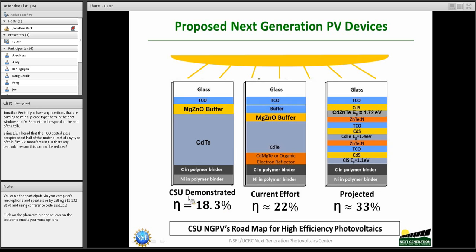And what we have demonstrated and verified by the Newport verification process is an efficiency of conversion of 18.3%, which is probably the highest that has been reported for this particular class in the literature. This compares very favorably in terms of conversion efficiency with multicrystalline silicon. And if you factor in the advantages of the lower temperature coefficient for cadmium telluride, it's actually better than silicon in terms of converting sunlight to electricity.